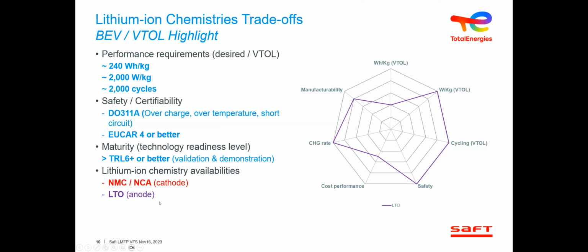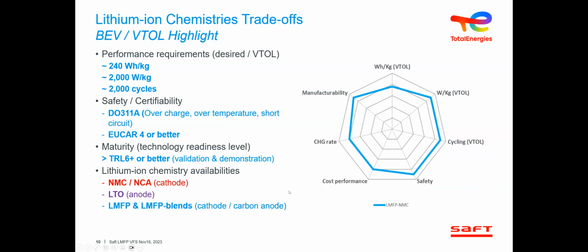On the LTO, the anode is a titanium oxide type anode, and allows for different behavior, a different specific construction that allows for very hard charge rates and very high cycling. So the cycling ability is unmatched with over 20,000 cycles. But the low voltage makes this technology have very mediocre specific energy, with good power capability. It's able to release its lithium very easily. Very good safety thanks to its very strong stability and the lack of certain characteristics in the electrochemistry. So it can charge, be safe and powerful, but cost-wise it's an expensive technology, and voltage-wise, there's a low operational voltage, which makes it not so good for specific energy.